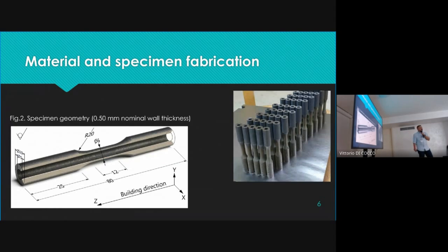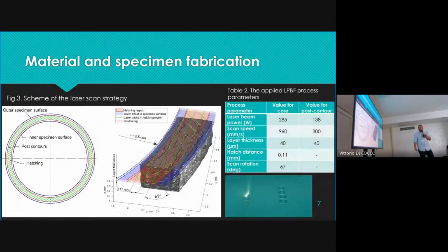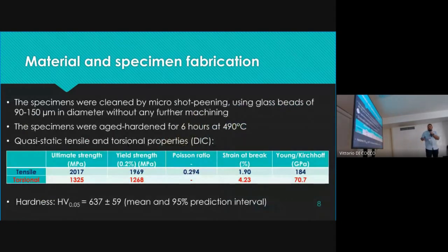We made more than 300 specimens of that type, and the laser scan strategy was as shown on the slide, with a 67-degree angle change between the layers and additional contouring on the outer and inner diameter of the specimens. On another slide we will see the effect of the contouring. After the printing, the specimens were cleaned by shot peening with glass beads of around 90 to 150 micrometers diameter, and no further machining, nothing else.